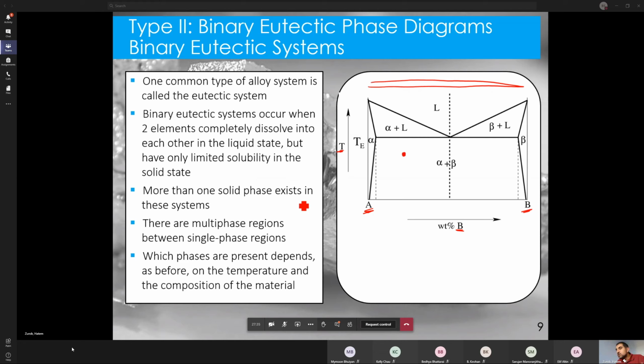But interestingly, in the solid, A and B do not always mix. Let's take an example. If this is A, this is pure A over here. I can put a little bit of B inside A. For example, if I have this composition here, 5% B, 5% B can completely dissolve in A. But if I keep adding B, if I go to this point instead, what happens now? The diagram says you have two phases, alpha and beta. Now, what are alpha and beta? Well, alpha is a solid and beta is another solid. So those two solids would have, for example, different crystal structures. For example, alpha could be FCC and beta could be BCC.